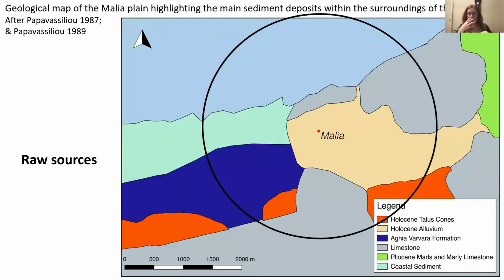elemental composition. But even samples such as Ma2, that show peaks that are quite foreign to the other samples, such as dolomites and iron oxide like magnetite and hematite, can be reconnected to geological sediments that are present within this 2-kilometer radius. In the specifics of sample number 2, the limestone geological deposit, as well as the Agia Varvara formation and talus cone, are present on the west and the south of the site.